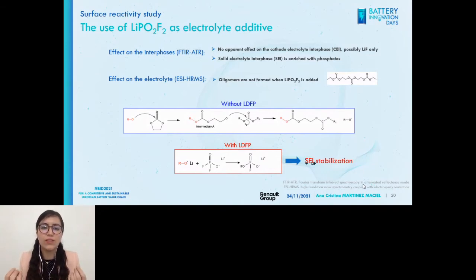And on the solid electrolyte interface, there was an effect - we saw that it is heavily enriched with phosphates when LiPO2F2 is used. And regarding the effect on the electrolyte, we saw that oligomers, this molecule that you see on the top right, were not formed when LiPO2F2 is added. So this is how we were starting to see what the mechanism of this additive is.